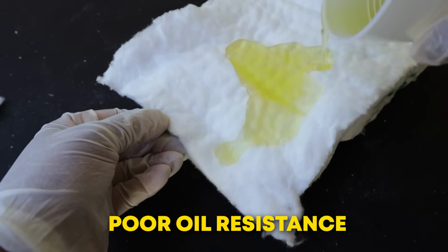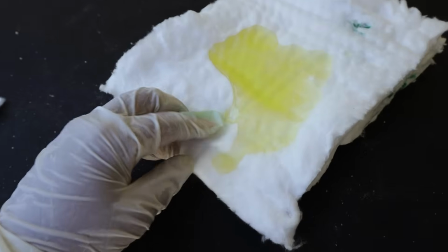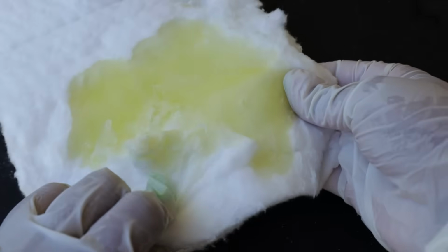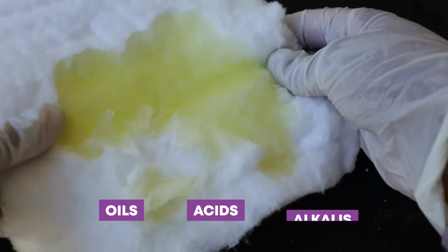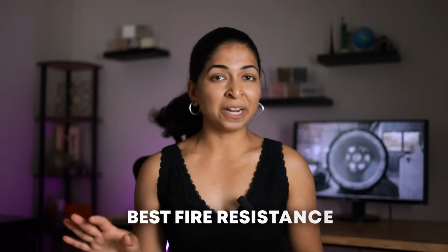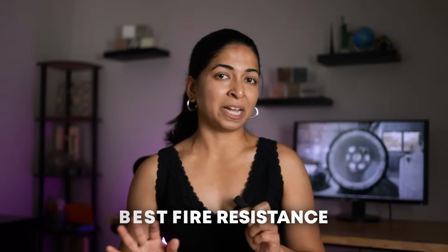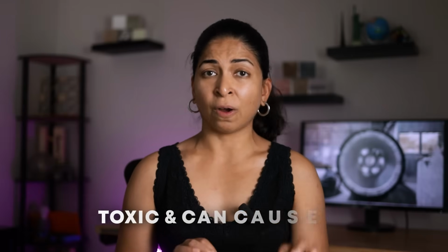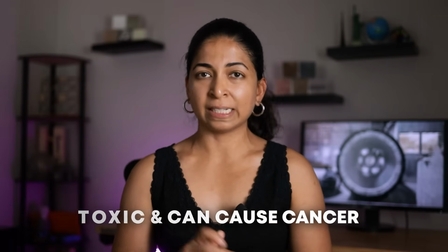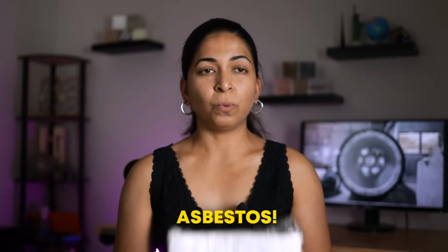It also performed very poorly to oil, even though ceramic fiber insulation is supposed to have excellent resistance to oils, acids, and alkalis. This material has a very particular set of skills. It has the best fire resistance among all the different types of insulation I have tested, but it fails in most other areas. The fact that it is toxic and can cause cancer is very concerning. I have read some research papers that liken this material to asbestos. Workers who manufacture ceramic wool and even those who work at kilns are exposed to these fibers on a daily basis, which puts their health at risk.